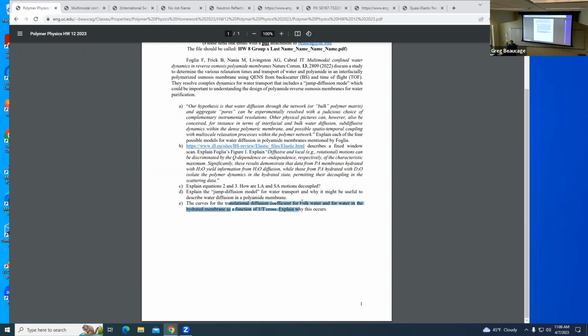That should be your friendly point in these complex papers. You find something log versus 1 over T, and you know what that is. They'll get an energy, an energy of something happening. And then you ask what is happening. If it's a straight line, it confirms that it's a thermally activated process.